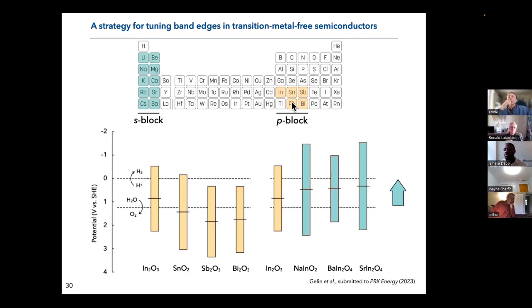And so if you combine electronegative elements together, the band gap that you're going to get is going to be very small, meaning that you're going to be able to absorb solar light. But the problem with those materials is that because they're very electronegative, they don't give away very easily their electrons. And this translates in the fact that their energy levels are very low, meaning that it's very difficult to extract electrons from those materials. And so the materials that we obtain are often ternary oxide of P block and S block. So in a sense, it's not surprising. You want to have S block, very electropositive metals in order to counteract that tendency of the semiconductor to not give away this electron. So as soon as you mix those initial binary oxide with S block element, you see that you have a shift up of the band edges.